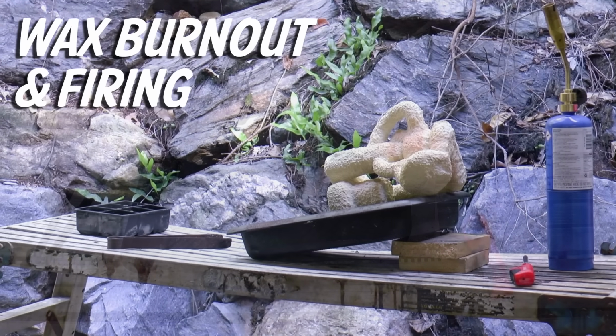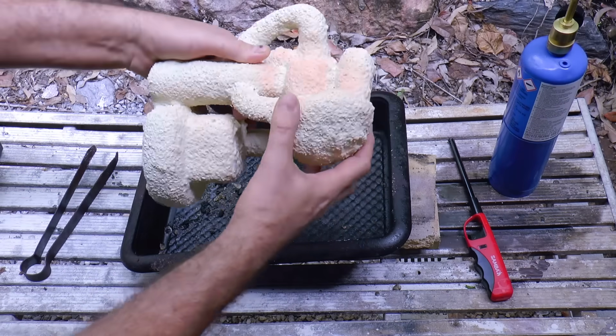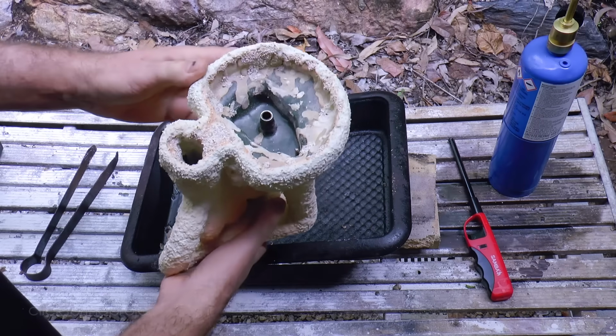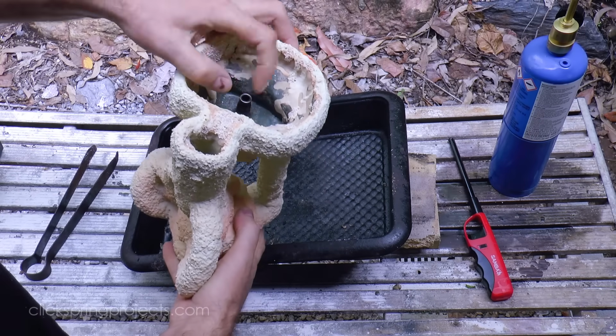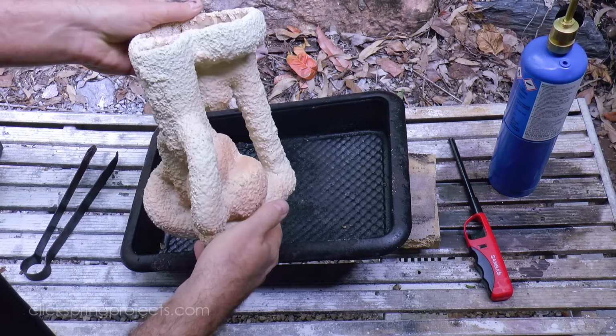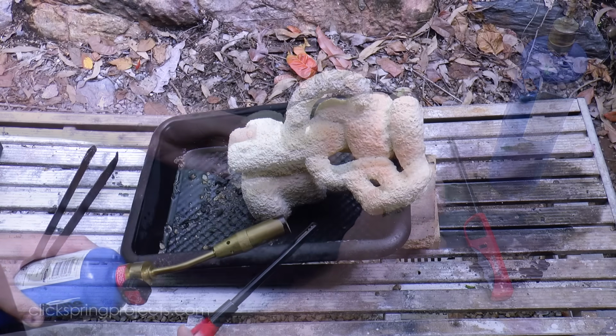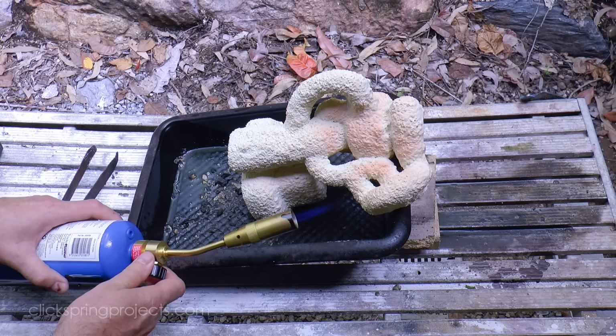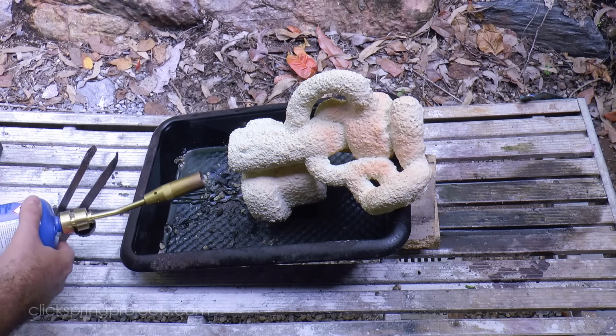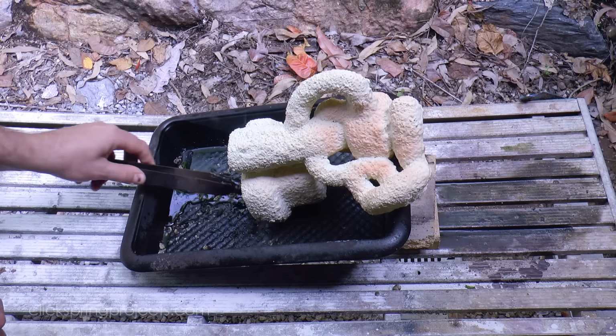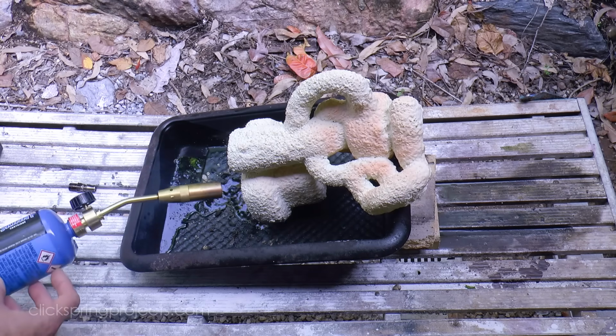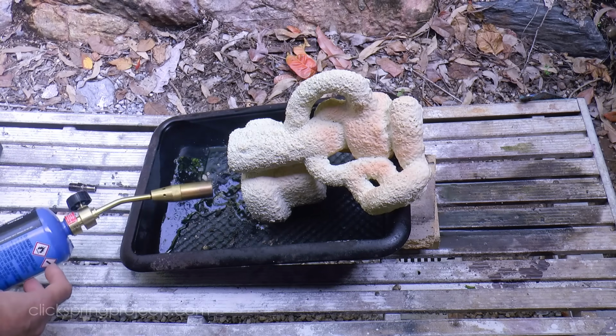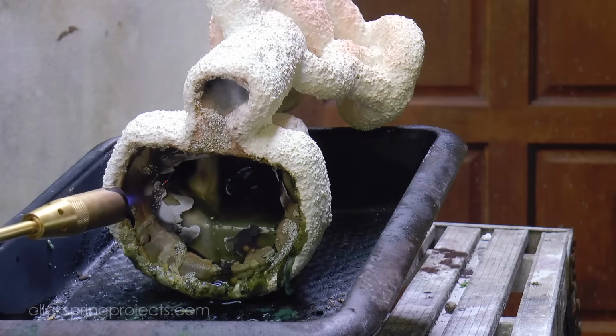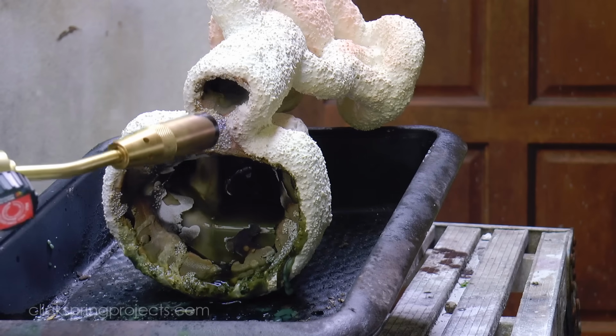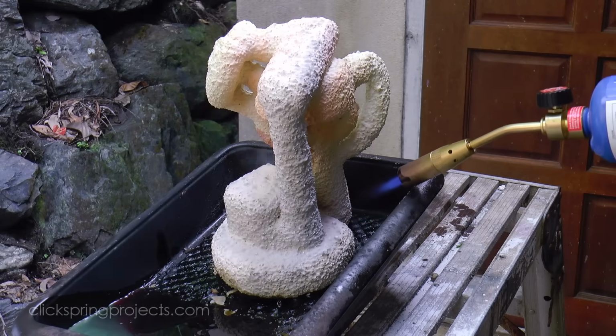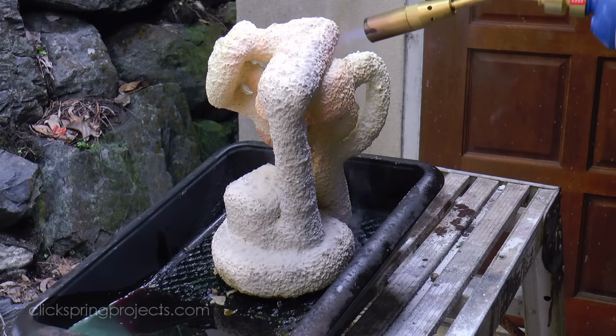Okay, so once the mould has fully dried, the next step is to remove the wax. My kiln is not designed to burn large quantities of wax, so I use a simple baking tray and a torch to do most of the job. The main objective here is to remove as much wax as possible from the mould before it enters the kiln for firing, and without igniting a wax fire. This means taking it slow and setting the torch flame relatively low to keep things sedate.